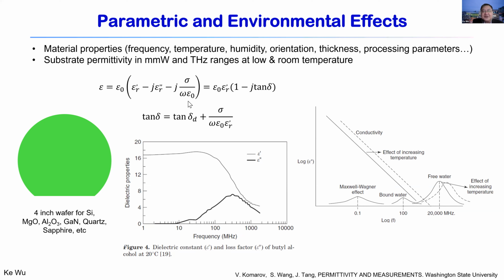But for most of these low loss materials, the epsilon r double prime doesn't exist, or it's negligible, because this is a frequency independent epsilon r double prime, usually over a certain frequency range, of course. But the conductivity represents a leakage due to the imperfection of the materials or the crystalline structures.